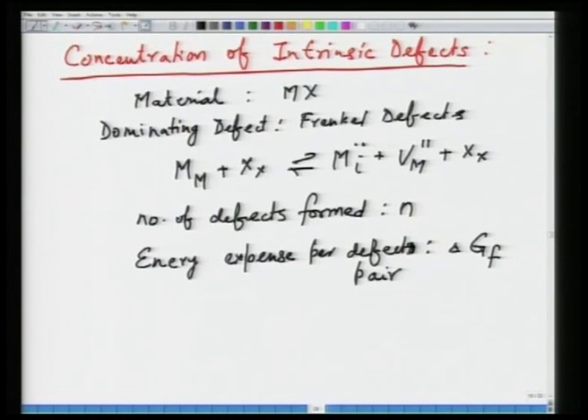So, energy expense per defect pair is delta GF. So, what is the net free energy change? So, delta G from a 0 defect state to, let us say, n defect state is equal to G minus G naught. G naught is the defect free state. So, this would be n delta G f. So, this is your enthalpy change minus, at a given temperature, assuming that here temperature and pressure are constant, at this particular temperature, what is the change in the entropy?